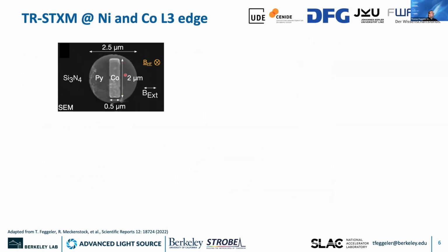We have a 2 micrometer length of the stripe and 0.5 micrometer width, and thickness is 30 nanometers, on a permalloy disk with a diameter of 2.5 micrometers, also with a 30 nanometer thickness.